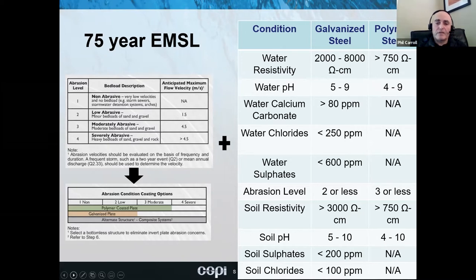The other thing to be careful of, if you go down to the bottom, is soil pH. It's quite common to pre-qualify the backfill that goes around the arch. Where you have soil pH of 5 to 10 and sulfates and chlorides less than 200 and 100, you can use galvanized steel. If you're looking at hotter soil, and you can't get more neutral soil, then you have to switch to polymer steel. So it's a bit of a tradeoff on this one slide, where you have to understand what you're dealing with: velocities, abrasion limits, as well as what's going through the structure and what the water's doing inside the structure.